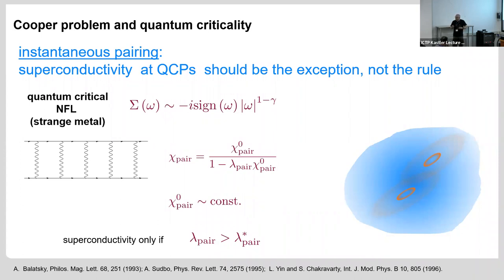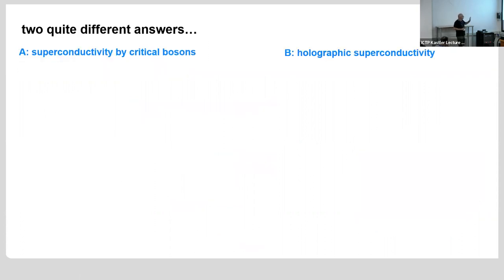This is worth discussing. There's actually a paper from Bardeen asking why sodium is not superconducting — sodium should be superconducting but apparently is not because of a poorly screened Coulomb interaction. There's no paper from Bardeen asking why sodium is not ferromagnetic, because we have the Stoner instability fulfilled and nobody is surprised we don't. So if this reasoning holds, quantum critical superconductivity should be the exception rather than the rule. There are answers to this problem, and I want to discuss two possible answers that appear completely different, and then show at the end that they are actually identical.